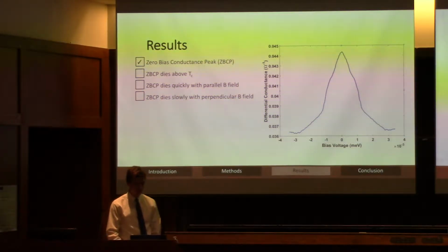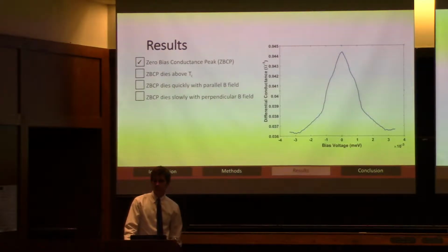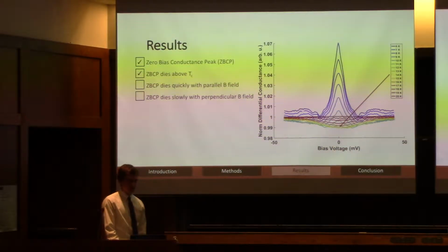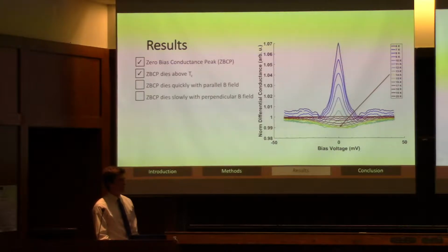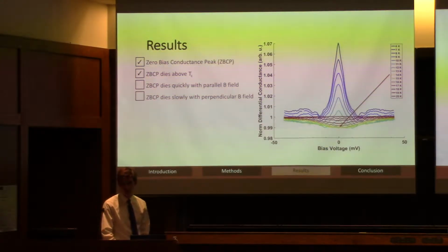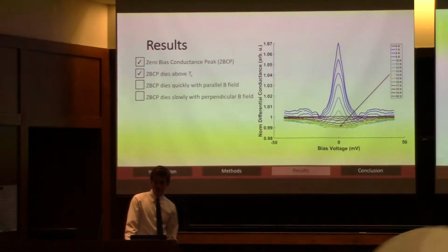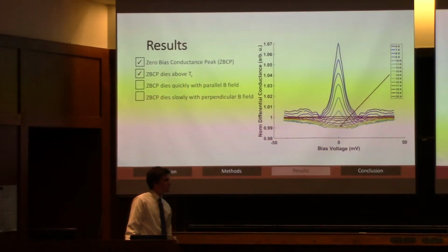We also want to see that this peak dies with temperature. So when you warm the sample out of its superconducting state, we want to see that new phase of matter disappear, because we want this to be a product of that superconducting condensate. And in fact, we see that as well. So again, this is differential conductance versus voltage, and each of these colored lines is a temperature. I have a line there pointing from 14 Kelvin down to the first line that doesn't show a peak, and that is right at the critical temperature of this sample. So that peak starts to die as you warm it up and disappears as it comes out of its superconducting state, and that's exactly what we want to see.